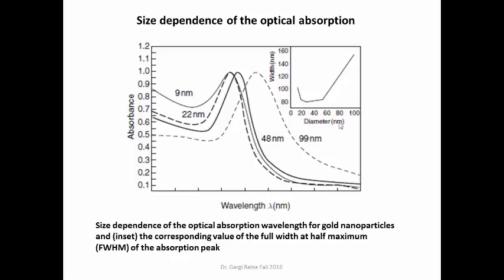This graph here shows UV-Vis spectra for gold nanoparticles of different sizes. As you can see, you have various spectra corresponding to different sizes of the gold nanoparticle. For instance, this solid line corresponds to gold nanoparticles of 9 nanometer diameter. The dashed line here corresponds to 22 nanometer diameter. Then you have another shifted solid line corresponding to 48 nanometer, and finally this small dashed curve corresponds to the 99 nanometer size particle.